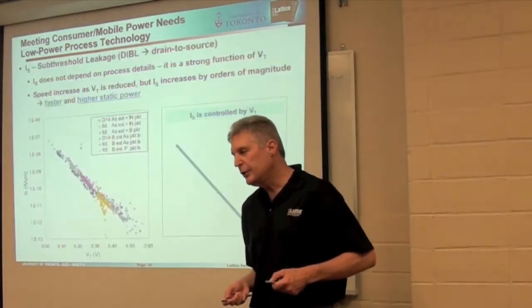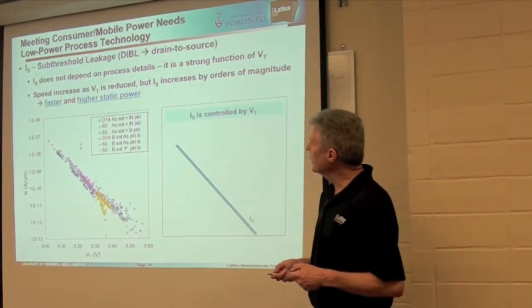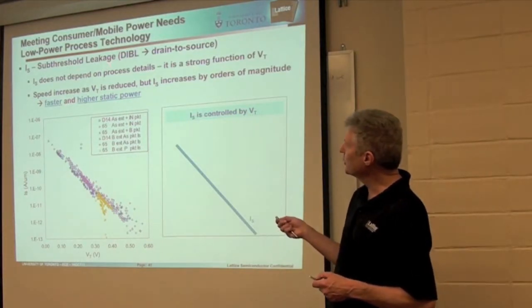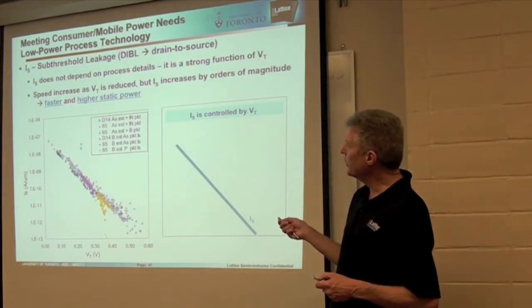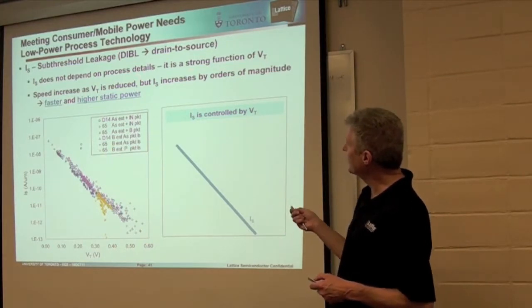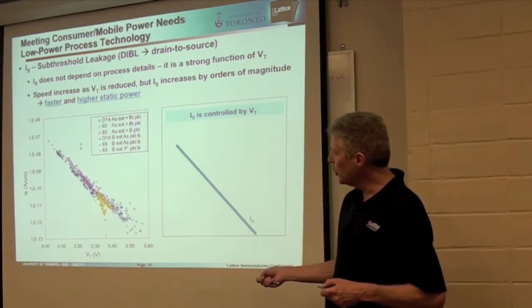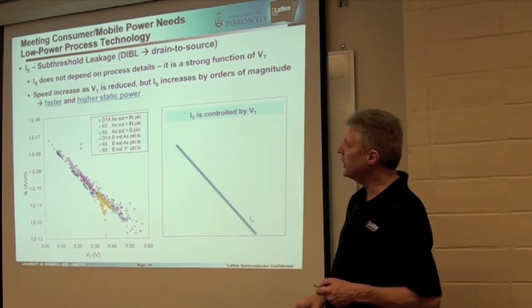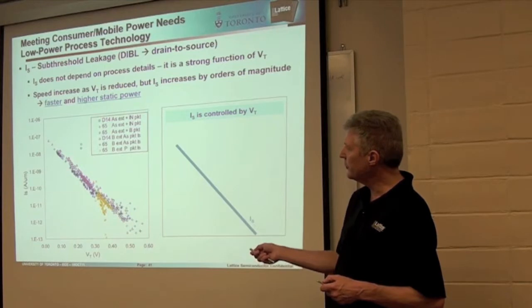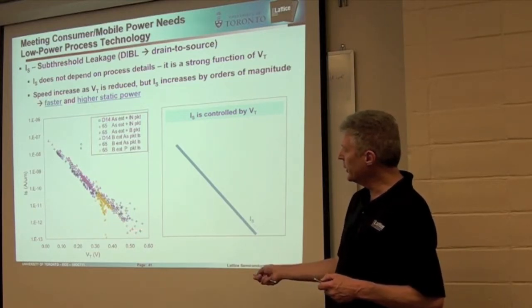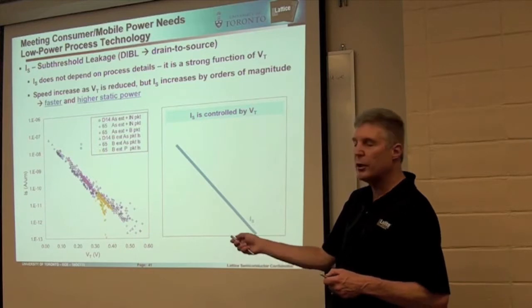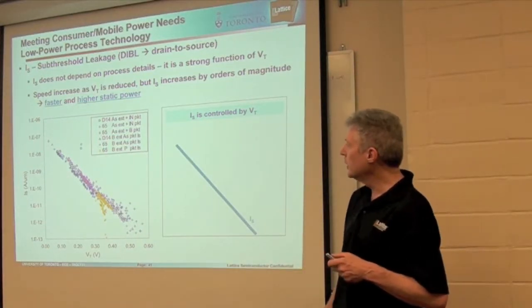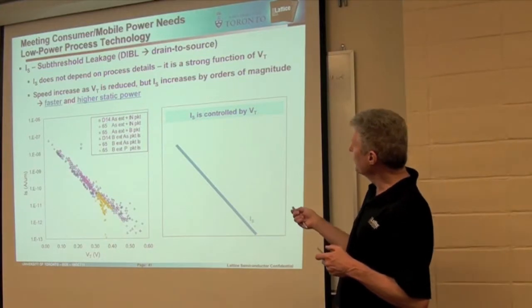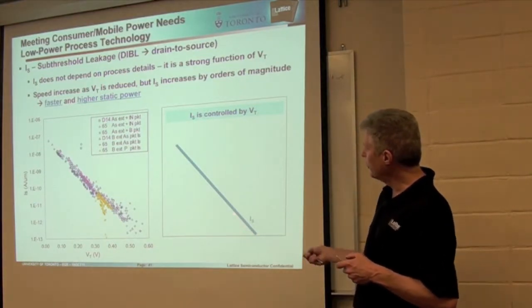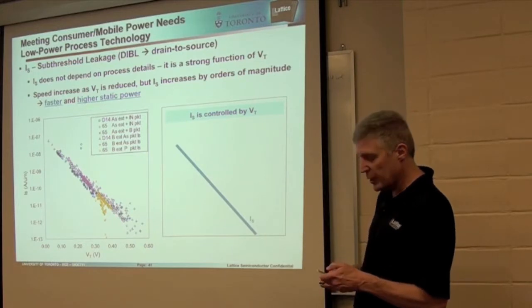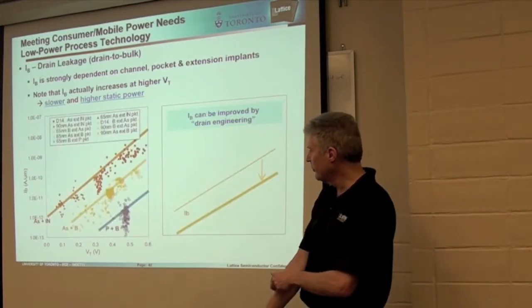I'll tell you what we've done in each of these areas. So, the first thing to highlight here, the first component, the subthreshold leakage. This really doesn't depend on the process details too much. It is basically just a function of the threshold voltage. So the lower your threshold voltage, the higher the leakage current, and you can see that illustrated here. And again, the exponential relationship I described, a linear change in threshold voltage translates to a logarithmic change in subthreshold leakage. So this characteristic, I'm just going to illustrate with this slope right here, and we're going to look at the next component and see how it reacts as a function of threshold voltage.